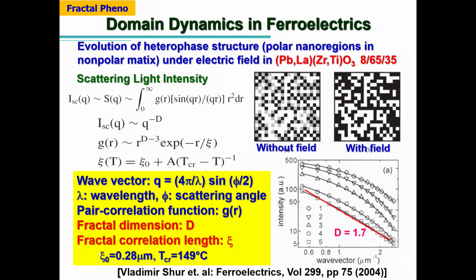And for the domain dynamics in ferroelectrics, this is cited from Dr. Shur's paper, and they worked on scattering light intensity measurement, and this is PLZT. They reported a fractal dimension of around 1.7. Just remember this number, I will introduce it again later.